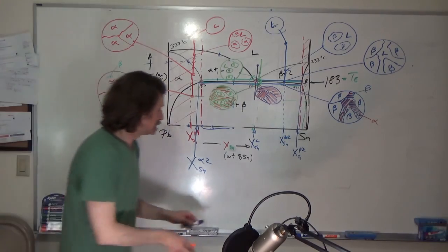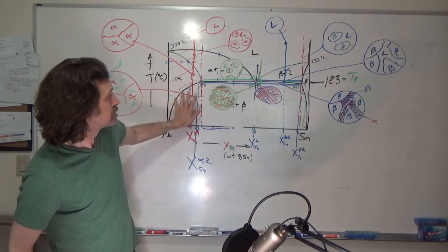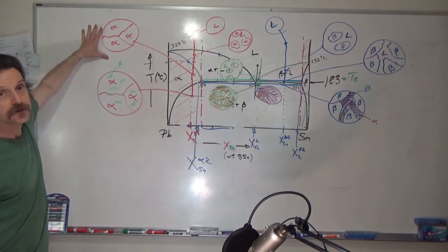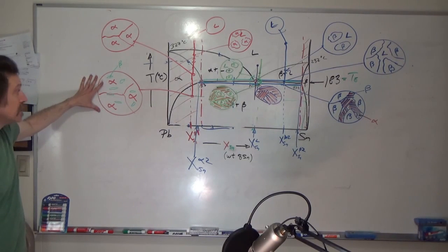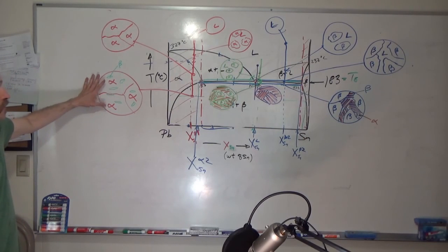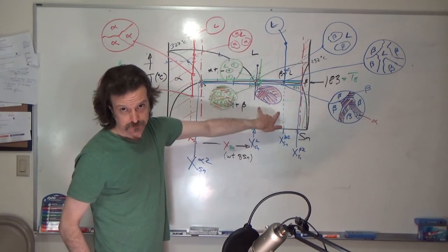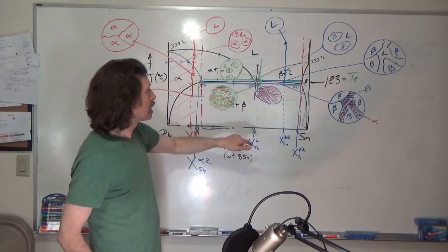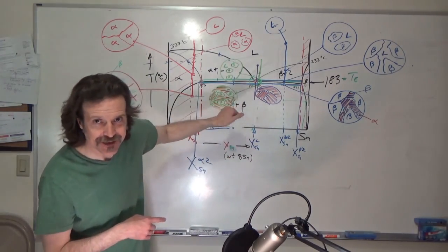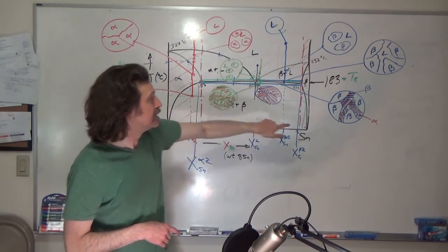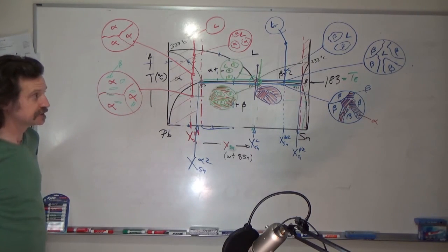So by selecting the position, we can control if we have, at room temperature, a microstructure that is large crystals with small precipitates, all eutectic, or a mixture of eutectic and crystals, and the size of these single phase crystals that form.